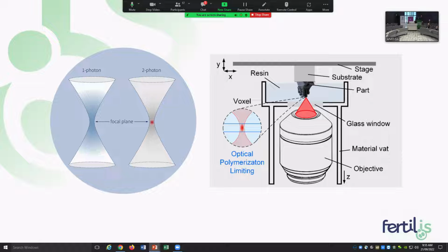So what are some of the design considerations when 2PP printing? For starters, adherence to the substrate is really important. If you don't get good adherence to the substrate, you end up with a mess, and a mess that you need to clean out of the vat. If you adhere too well, then you have issues with collecting your part at the end. Design geometry and printing orientation is really critical. Just like with filament printing, you need to be able to build up your layers and they need to anchor to each other, which then anchors to the substrate. Overhangs are not possible. And unlike filament printing, where you can build up a substructure and remove it afterwards, at this scale that's really not practical. So giving thought about how you design your part, how you orientate your part, and what surface you adhere to your substrate is really important.